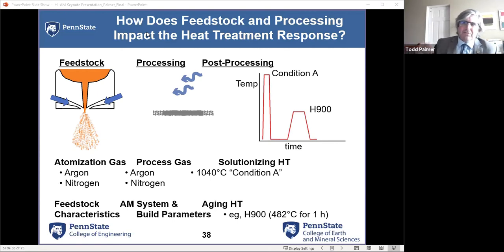is going back into fundamental solidification theory and really using Scheil-Gulliver type simulations across a liquid-solid two-phase region, looking at diffusion in the liquid, no back diffusion into the solid. At the rates that we're seeing in most of these, the Scheil simulations are doing a decent enough job. It's not perfect, but it's letting us see this partitioning.